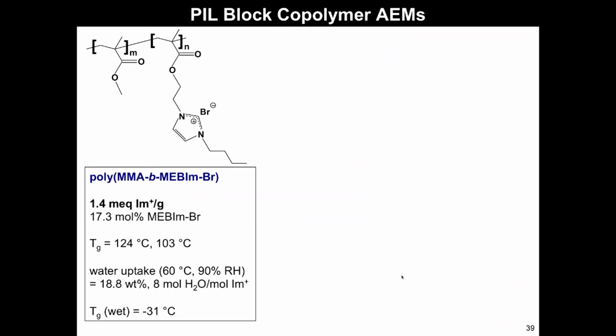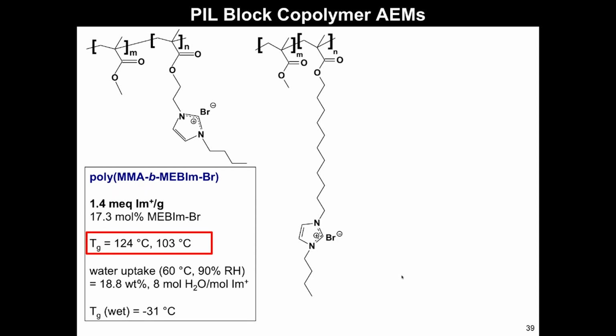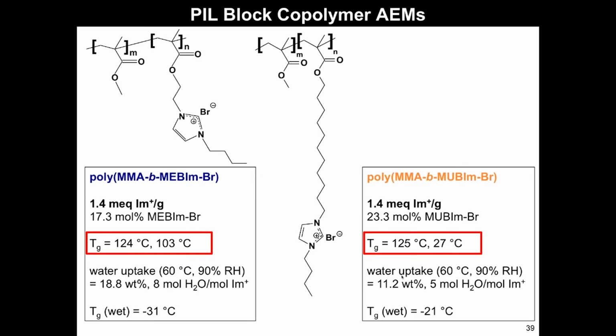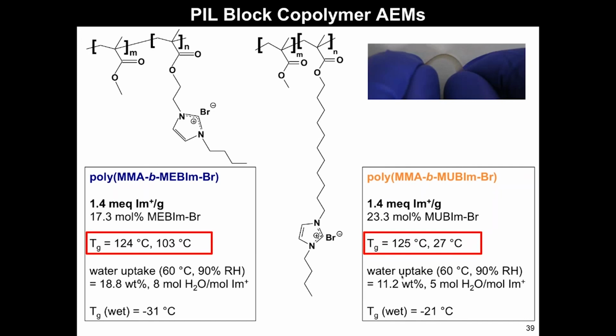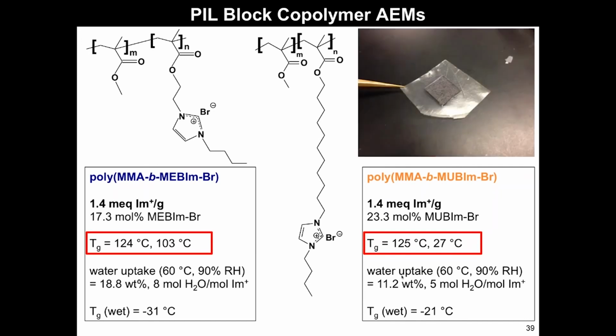And for us, from a practical application, this polymer under dry conditions actually had too high glass transition temperatures for the block. So it's actually very difficult to make films and stamp electrodes on each side for a fuel cell application. So one thing that we did, and we've done a number of things, but here's just one example, is increasing the chain extender here from 2 to 11. And you can see here, now the polymerized ionic liquid block has a lower glass transition temperature, and here you can make some flexible films and stamp electrodes on both sides for fuel cell testing.